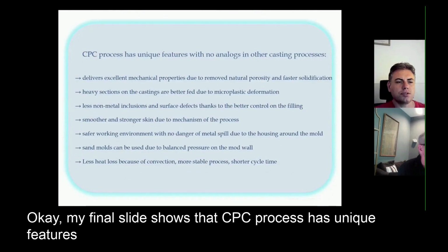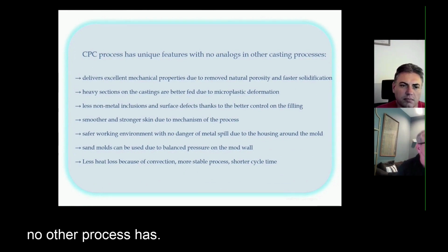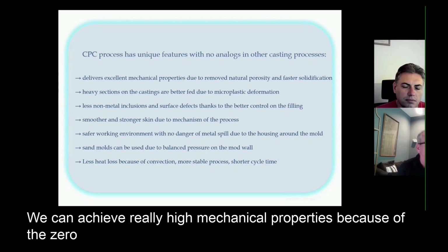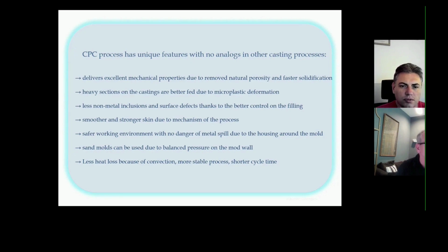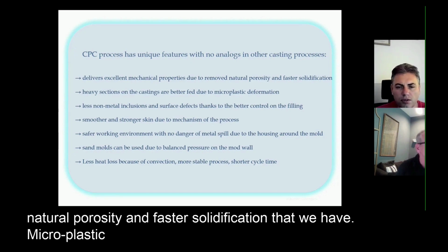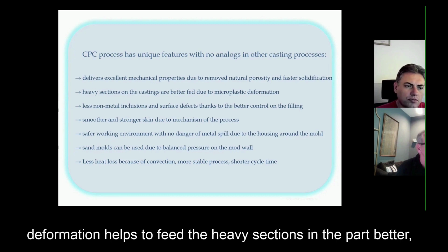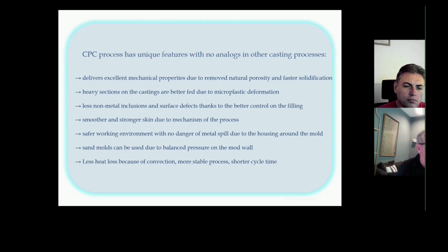Okay, my final slide shows that CPC process has unique features no other process has. We can achieve really high mechanical properties because of the zero natural porosity and faster solidification that we have. Microplastic deformation helps to feed the heavy sections in the part better, even through thin walls.